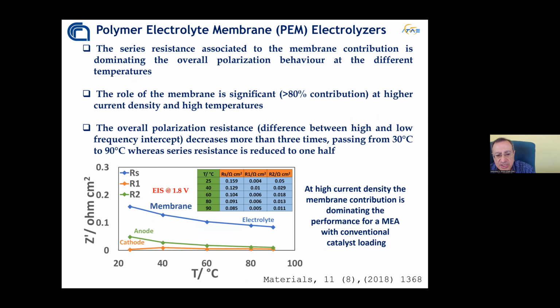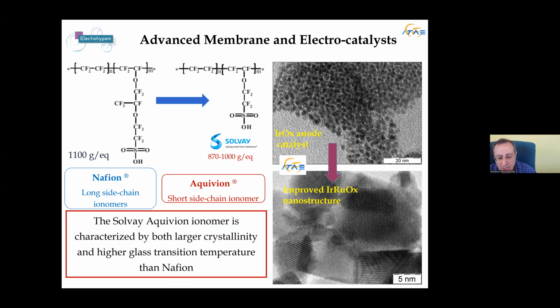Of course, these results can be plotted as a function of temperature. In this case, we can see that the membrane is dominant compared to the anode and cathode contributions in terms of resistance.